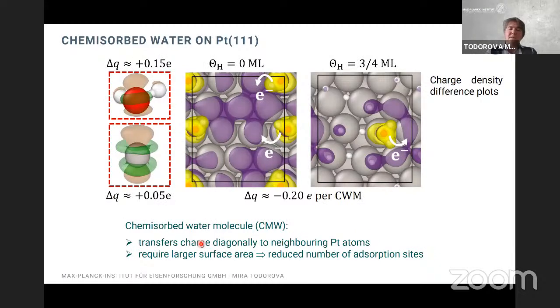Now, we looked at the charges that we have, and to our astonishment, we found that the platinum atom also loses electrons. So there is not really a charge transfer from the water molecule to the platinum atom directly below it. But what we found is that the charge transfer is to neighboring platinum atoms. And this was interesting, also regarding how many water molecules we can adsorb on the surface, because this means that each water molecule requires a bigger surface area than just one platinum atom to adsorb. And this reduces the number of adsorption sites.